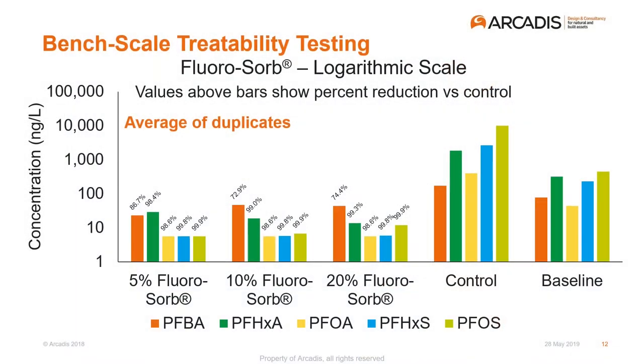When we look at it on the logarithmic scale, purposely, so now we're on orders of magnitude difference, it shows that there was slightly more or slightly less removal affinity of the short chain, which is not uncommon. That's one of the characteristic limitations of adsorption-based technologies. If you look at most new novel adsorbents, typical of the bellwether is PFBA, the C4 carboxylic. If it's adsorbing that, then that's a very good sign. And 86, 72, and 74% reductions when we're starting with concentrations at the PPB level is very good performance from a risk management source zone mitigation type strategy.